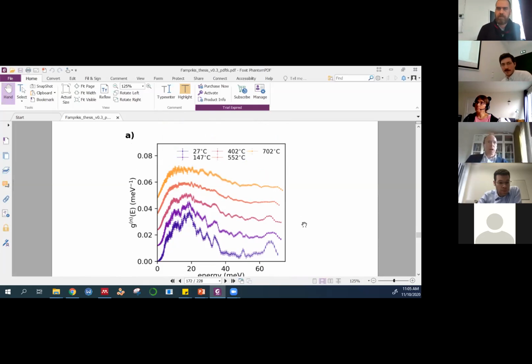So then maybe as for now, final question, if I'm still allowed. That was a lot about the intriguing sodium 3PS4. Now a bit back to the general challenges of solid state batteries, and maybe it's not a surprise to ask about the stability window. So I think it's the end of page 55 in your thesis, starting also on page 56. You describe the thermodynamic stability, which is basically comparing the free energy of your solid electrolyte with your decomposition products, and thereby you can construct an electrochemical stability window.